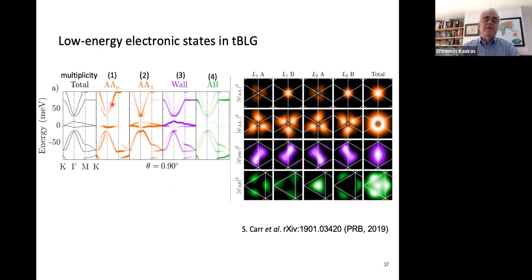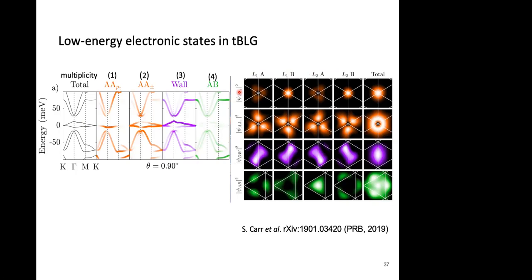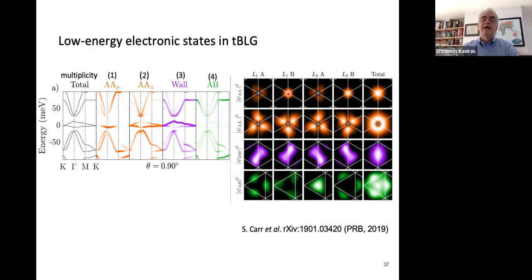So the orange parts correspond to wave functions that are near the AA regions. So here I have projections of the bands in different layers. So this is layer 1 sublattice A, layer 1 sublattice B, layer 2 sublattice A, layer 2 sublattice B, and the last column is the total wave function. So the orange parts are near the AA regions. So here again you see this pattern of high energy AA stacking. The low energy stacking are the black regions, and the domain walls in between. So the purple bands are on the domain walls, and the green bands are on the AB or BA regions.